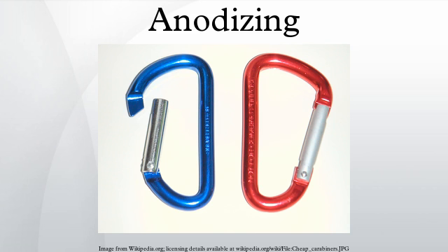Also, in the case of small holes threaded to accept screws, anodizing may cause the screws to bind, thus the threaded holes may need to be chased with a tap to restore the original dimensions. Alternatively, special oversized taps may be used to pre-compensate for this growth. In the case of unthreaded holes that accept fixed diameter pins or rods, a slightly oversized hole to allow for the dimension change may be appropriate.